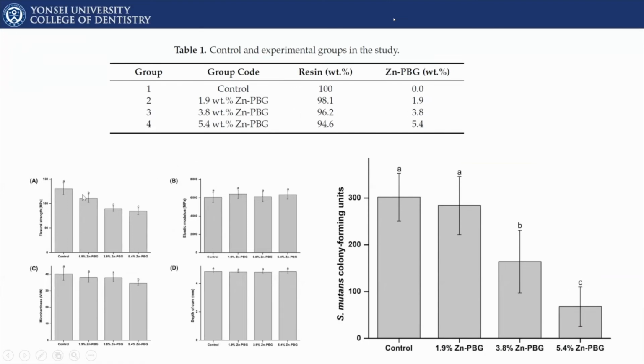And by adding it, obviously, up to a certain point, it decreases flexural strength, but it did not really have an effect on elastic modulus or depth of cure, and had a very minimal effect on the microhardness. But certainly, in line with our aim, the addition of zinc-based phosphate glasses reduced the Streptococcus mutans CFU, as you can see here, showing an antibacterial effect. Perhaps the reason is the release of zinc ions from these glasses in the resin matrix to the outside.